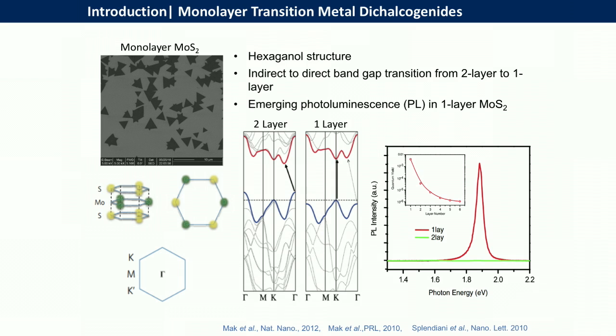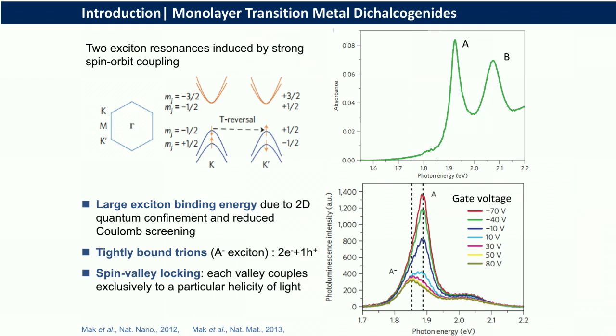The quantum efficiency of this light is very weak because of many factors, including many decay channels and non-radiative pathways. But nevertheless, compared to a bilayer, you can see this is a bilayer emission and this is a monolayer emission. It's much stronger. So there's a lot of interest in these materials, and again, a lot of good work has come out from this university. When you go to a monolayer level, you break the inversion symmetry, and the time reversal symmetry is maintained, as long as you don't apply a magnetic field. Because of this, there's a very interesting splitting in the two valleys, K and K prime.